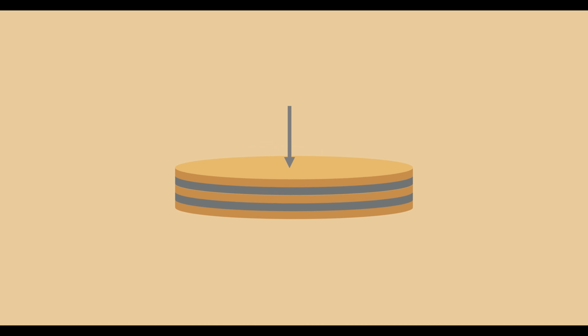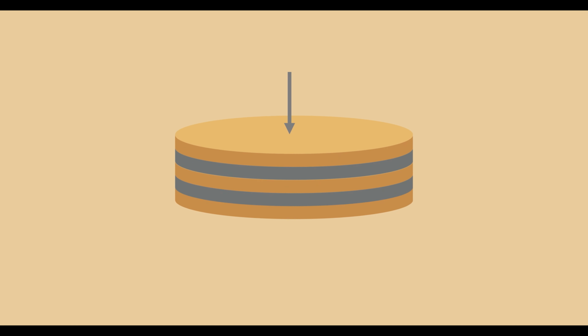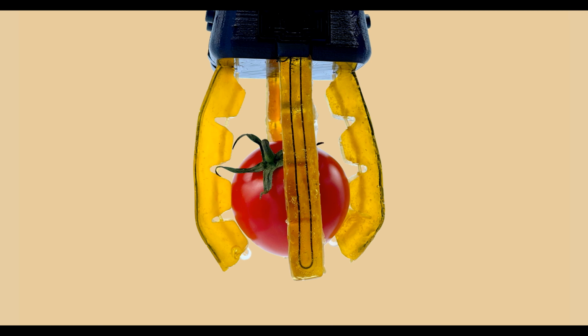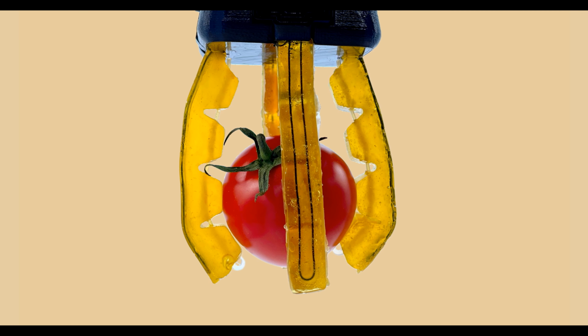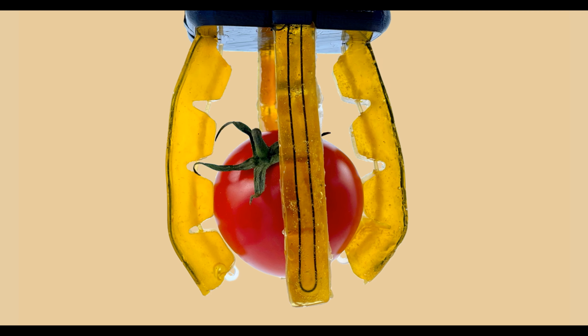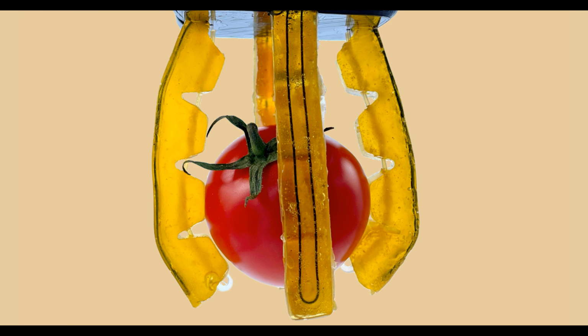By constructing a sandwich structure of two conductive layers separated by a non-conductive layer, a flexible parallel plate capacitor is formed. When compressed, these plates come closer to each other, increasing the capacitance. This principle can be used to measure the force exerted on grasped objects. All these sensors have proven full recovery of sensing behavior even after severe damage several times in a row.